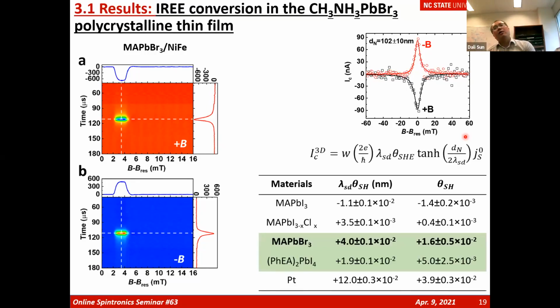But that's for the MAPbBr3. We also do multiple thin films to study their spin-to-charge conversion efficiencies and calculate the spin Hall angles, demonstrating their different spin-orbit coupling strengths. Surprisingly, we found that even for all these hybrid perovskites, where the spin-orbit coupling is supposedly dominated only by the lead, the spin-to-charge conversion efficiency changes from negative to positive, from a small value to higher values in MAPbBr3, even comparable with platinum's spin Hall angle. But here it's only lead, diluted lead in the octahedral layers, acting like a strong spin-orbit coupling material like platinum. This really makes us ask why it happened.